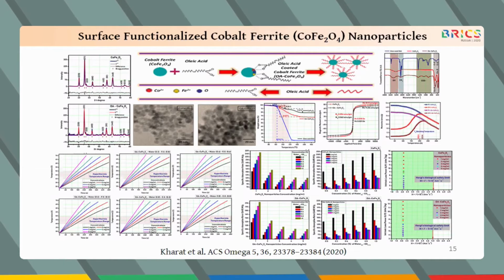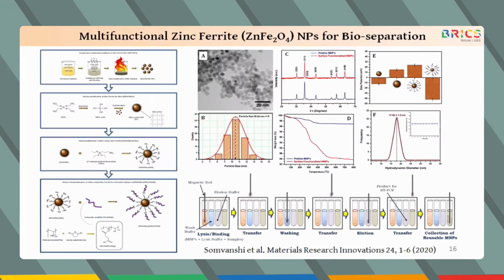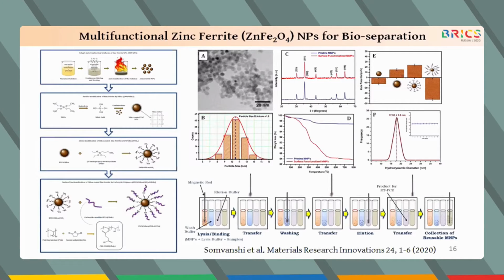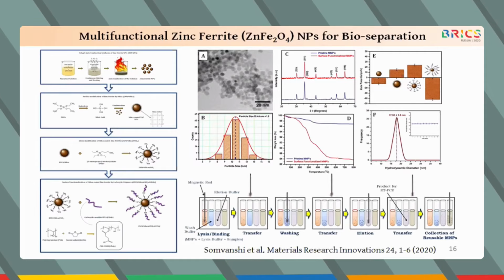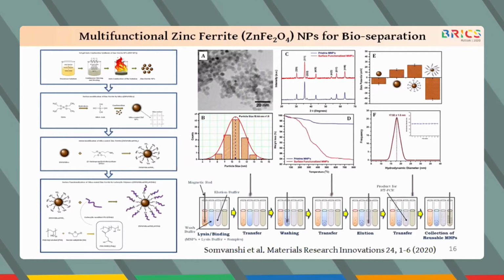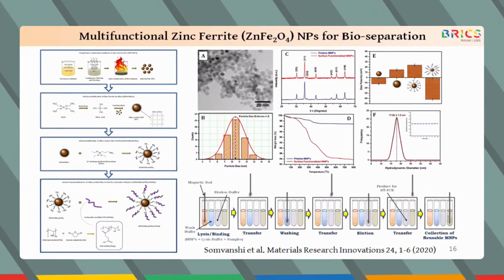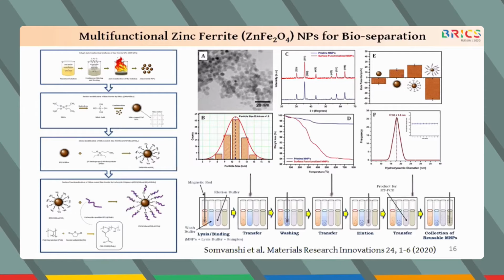Recently, we have also prepared multifunctional zinc ferrite nanoparticles for bioseparation process. In this study, the zinc ferrite core was coated by silica and polymer carboxyl group to make it multifunctional. And these multifunctional nanoparticles showed better results for the efficient and timely bioseparation.